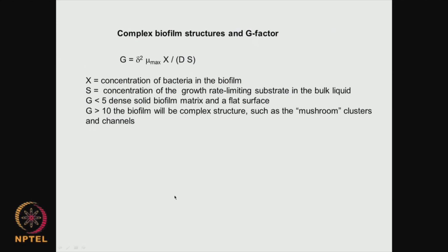So, that completes what I wanted to talk about on biofilm. We spent quite substantial time on biofilm because, as I said, it is the most important topic, especially in the area of biomaterial implants and devices. Many materials fail in early days because of formation of infection, biofilm, and development of persister cells which cannot be easily eradicated by simple antibiotics. The concentration of antibiotics required may have to go up by 10 times to kill the bacteria that are present and well developed inside the biofilm matrix, which contains exopolysaccharides and proteins and so on.